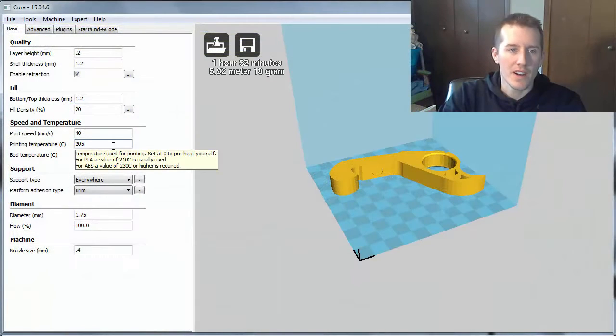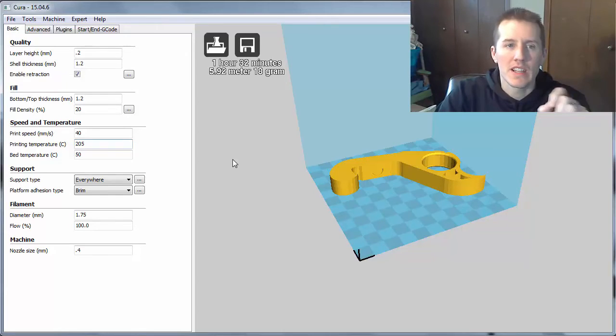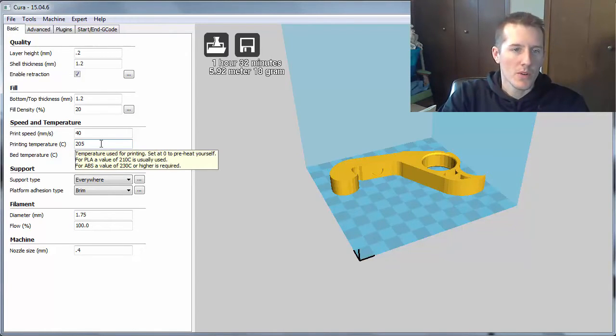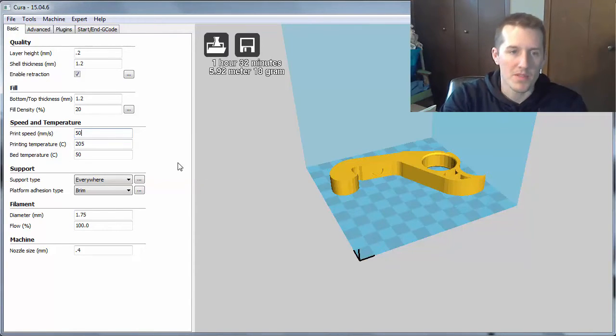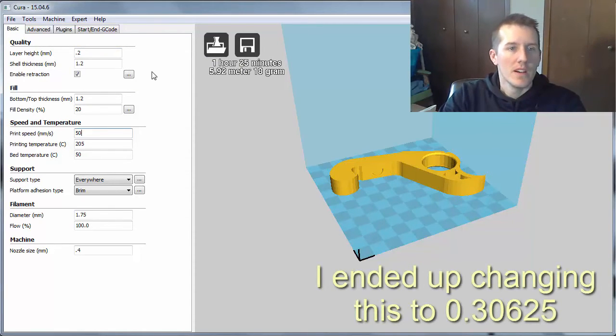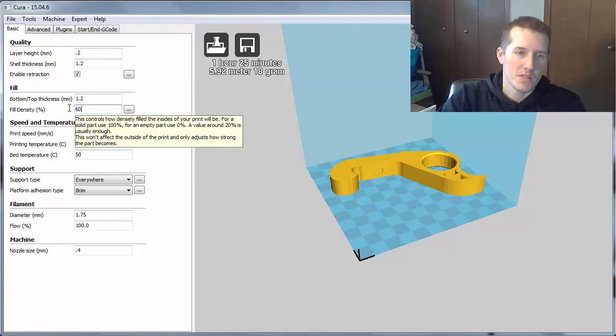I've tested it at 195 Celsius all the way up to 210 and they've all been great. If you want it even more accurate, use a little lower temperature. At 210, you might get a little drooping like on that Yoda print, so I might print at a little lower temp to get accuracy up. Anywhere around 200 to 205 will be fine. For bed temperature, it probably doesn't need a heated bed — it would print just fine on glass or blue masking tape, but I use the heated bed anyway. For this part, we could bump it up to 50. For layer height, 0.2 is fine.